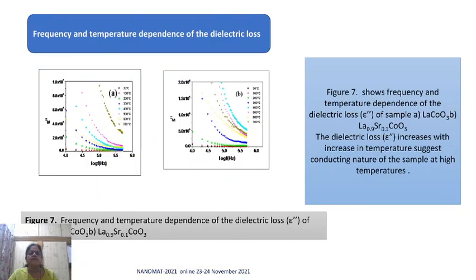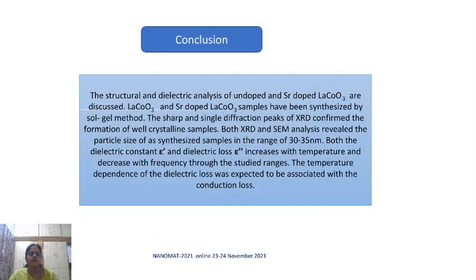The second is the frequency and temperature dependence of the dielectric loss. Figure A shows the temperature dependence of the dielectric loss of the LaCoO3, while figure B shows the temperature dependence of dielectric loss of Sr substituted LaCoO3. Here also you can see that the dielectric loss increases with increase in temperature, suggesting the conducting nature of the sample at high temperature.